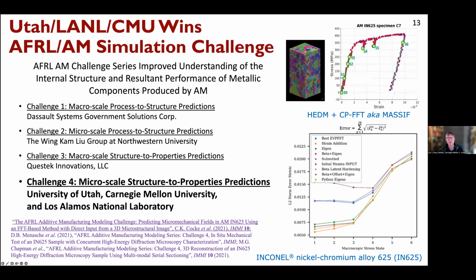So we started with these error values, so decent, getting less good as the plastic strain accumulates, but it was good enough to actually win that challenge, to our pleasant surprise. What was particularly interesting was to come back to the problem after the fact, after the selection had been made, scratch our heads and say, I wonder if we missed something. And sure enough, we did.